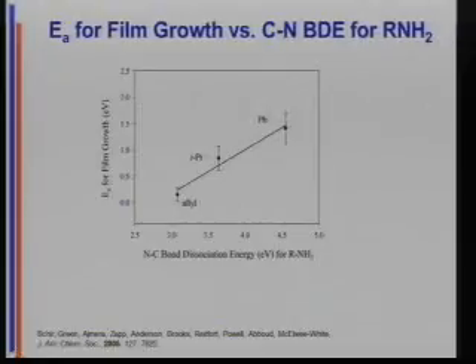So let's do chemistry. This is now a plot of the activation energy for film growth versus the CN bond dissociation energy. We run film growth kinetics by doing cross-sectional SEM. So we determine the film thickness in the cross-section and then work out growth kinetics from there. You can do this at different temperatures, do Eyring plots, and back out activation energies just like you do in any other kinetics. And take a look at this. The activation energy for film growth plotted against the CN bond dissociation energy, that's linear. There's your rate determining step for film growth: cleavage of that CN bond.